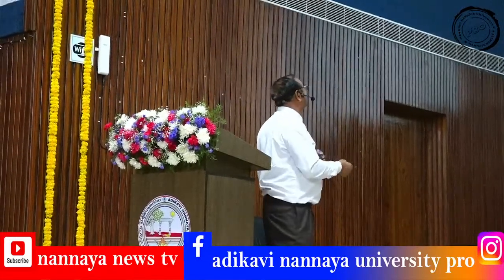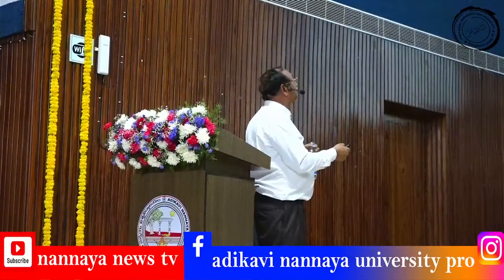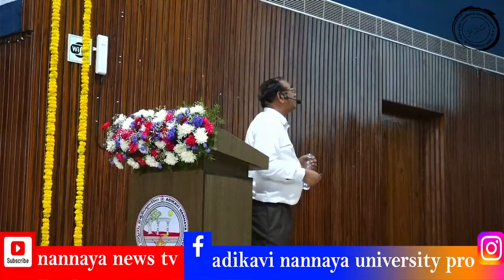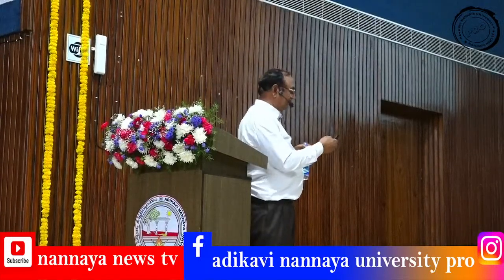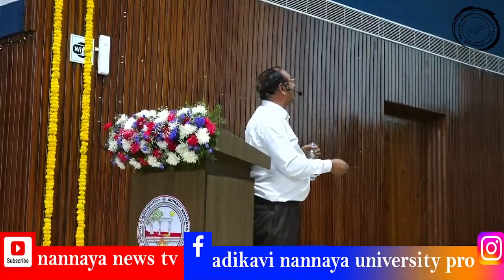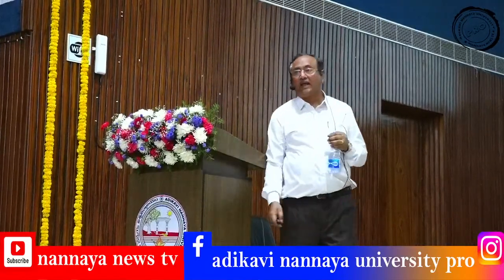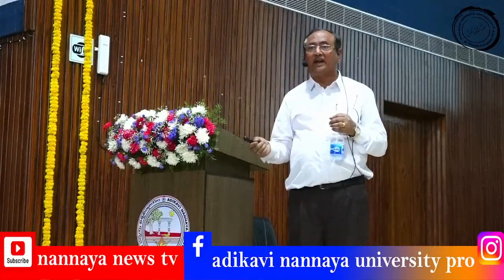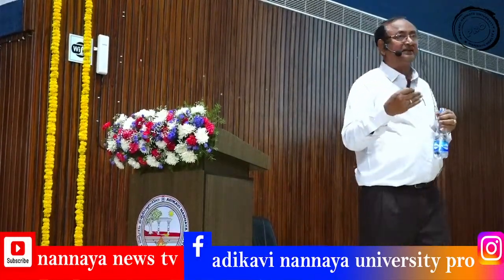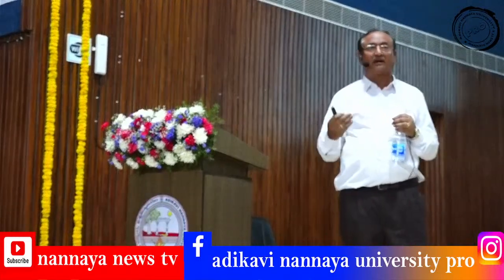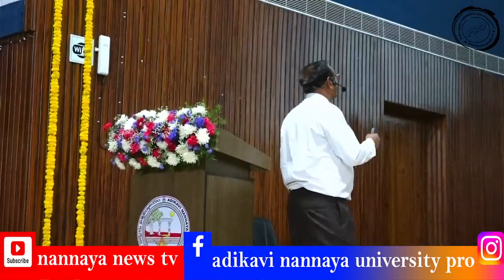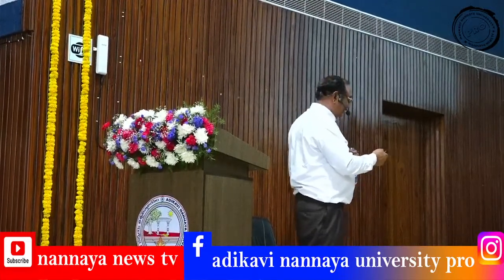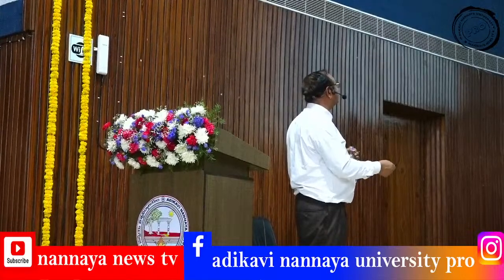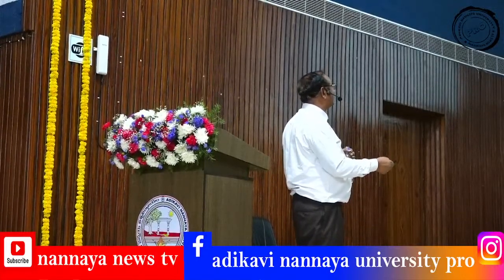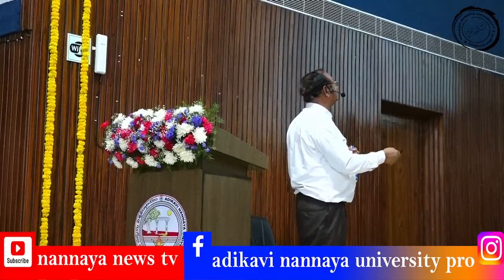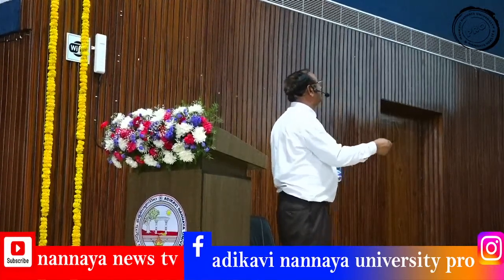Next slide, please. This is the Raman spectrum recorded for urea-doped zinc thiourea sulfate. Actually, in urea and thiourea, the atoms are the same. So therefore, no elemental analysis instrument will give any indication whether urea is doped in the crystal or not. The only way is by FT Raman or FT IR also. So here you see the only difference is that in urea there is a CO bond, and in thiourea a CS bond. So they have a different absorption spectrum.